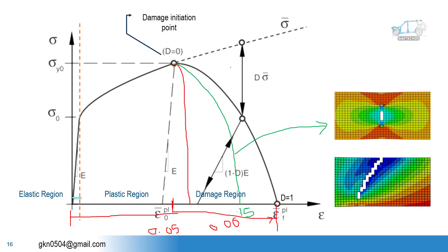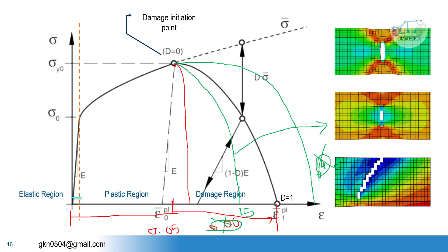So if you define a further high fracture strain — for example 0.4 — for aluminum that is a false, wrong value. Similarly, 0.06 is also not the right value. So if you have the proper material conditions and parameters, you will get a better result. But if you are defining those parameters randomly, you must take care of the fracture strain value. Do not define a value very close to the plastic strain — if you do, this will behave like a brittle material. If you define a very high value of the fracture strain, this will behave like a rubber-type material.